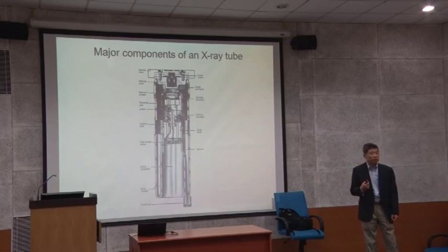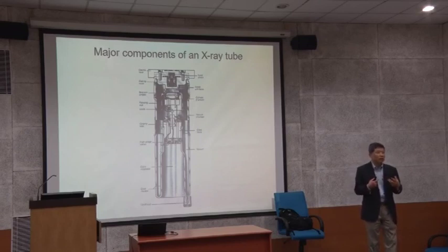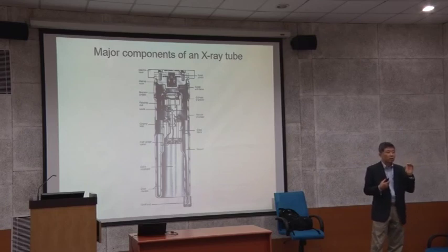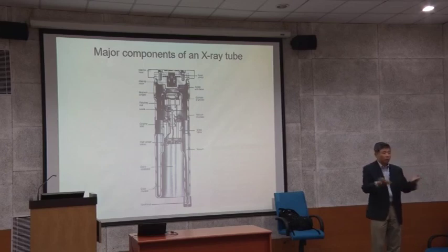One major source of X-ray is a simple vacuum tube. It's a vacuum tube with two vacuum windows on both sides, and a fixed target. The flux is limited by cooling of the fixed target. So usually the X-ray source people use has a copper target with a tungsten filament on top. You heat up the tungsten filament to generate an electron flux, and the electrons accelerate through an electric field of roughly 40 to 50 kV, high voltage. Then you hit the target, and X-ray comes out.